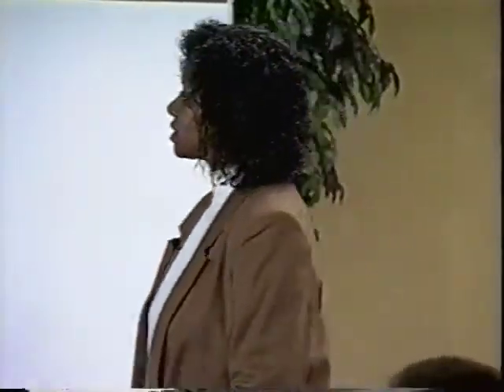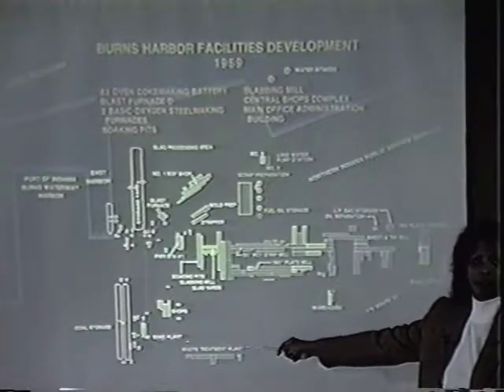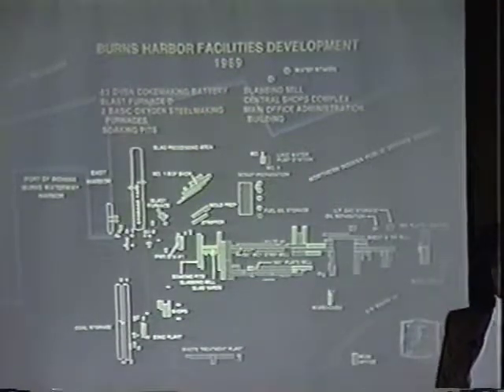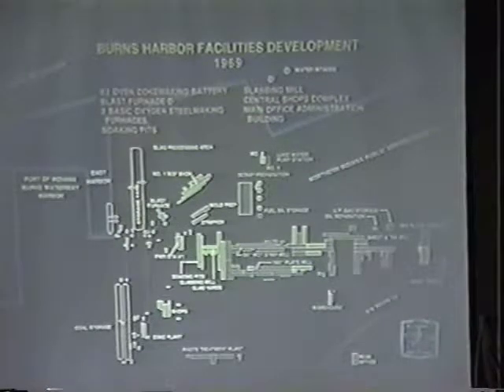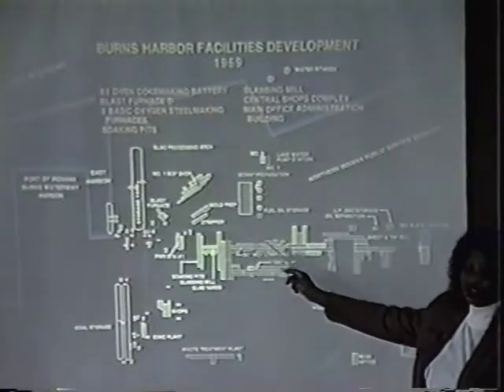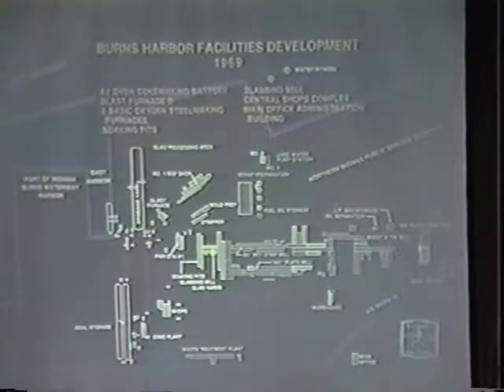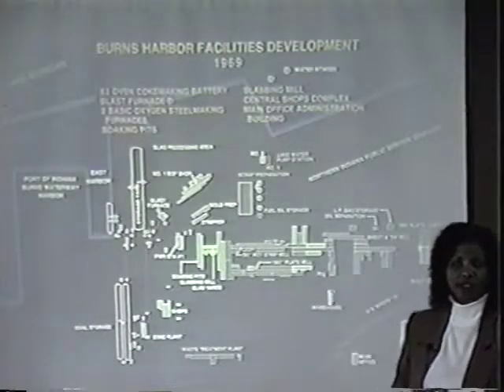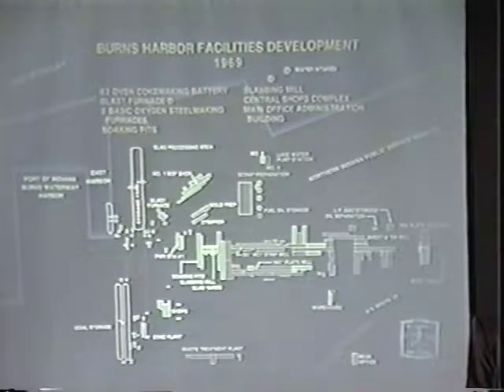In 1969, we became a fully integrated steelmaking facility, which allowed us now to make our own raw steel product of a slab that we could now feed into our finishing mills. We started up one coke battery with 83 ovens, one blast furnace to convert the iron ore pellets into a liquid iron or a hot metal product. That blast furnace's rated capacity at the time was about 3,500 tons of hot metal per day. Our steelmaking shop had 2 BOF vessels in them. BOF again refers to basic oxygen furnace. We did not have continuous casting technology at that time, so we built all of these support facilities to actually make our slabs by the ingot teeming method.